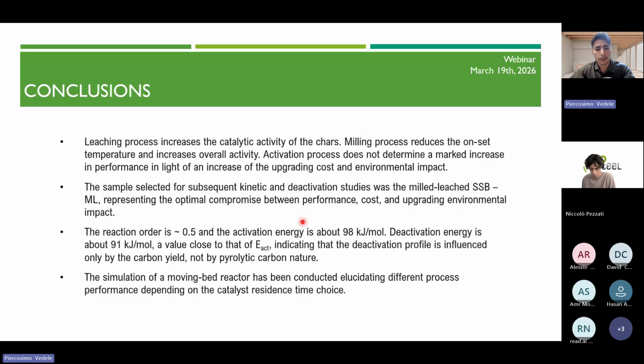So, in conclusion, we tested several biochars from the family of the sewage sludge, which were subjected to different upgrading processes. The leaching, the milling and the activation, of course, increase the activity of our catalyst. In particular, the activation only slightly increases the activity of our catalyst. For this reason, we decided to proceed with our further study with the milled leached one, only because it represents the best compromise between performance, cost, and environmental impact of the upgrading.